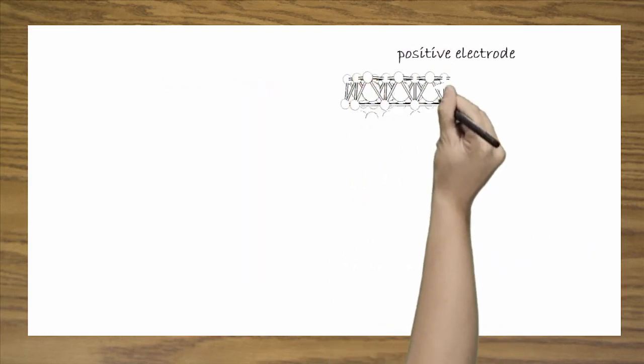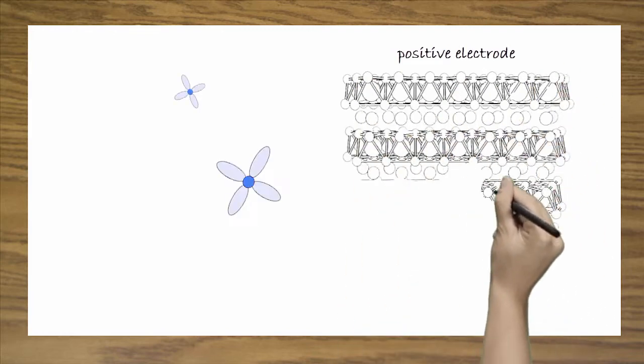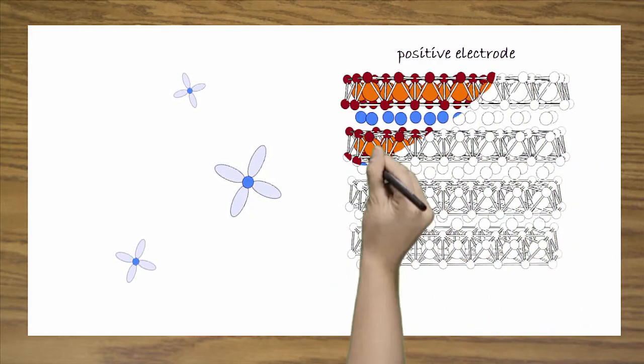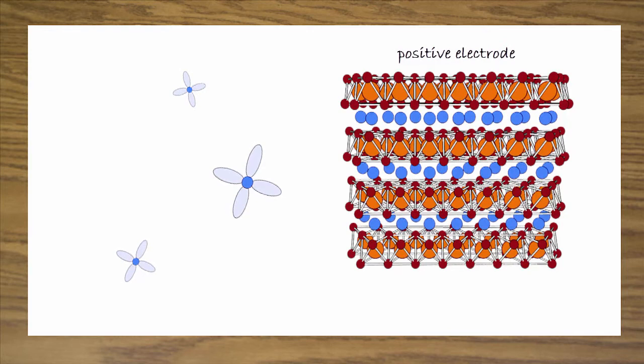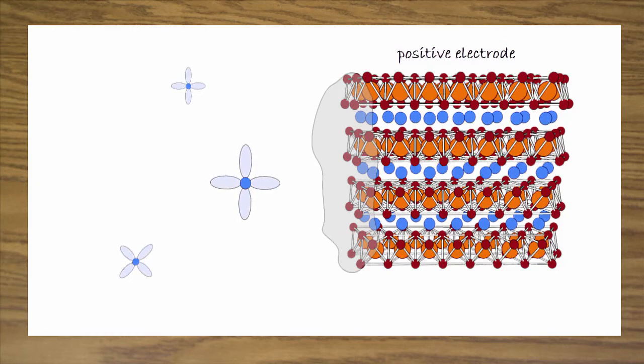Now, what about the interface on the positive? The positive electrode is generally a lithium layered oxide, such as lithium cobalt oxide. The interface at the positive side is kind of a gray area in the literature. Thermodynamically, there should be no oxidation of the electrolyte up to potentials close to 4.5 volts, and we should thus not observe any decomposition of the electrolyte through electrochemical reaction.